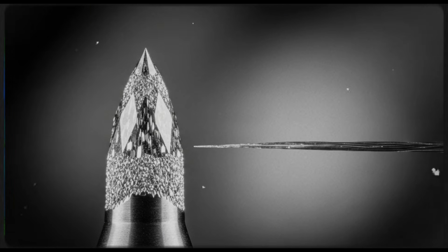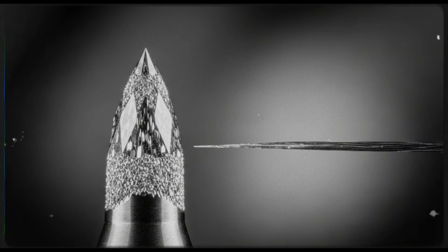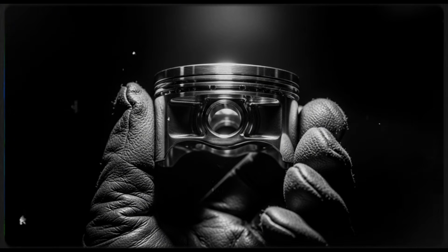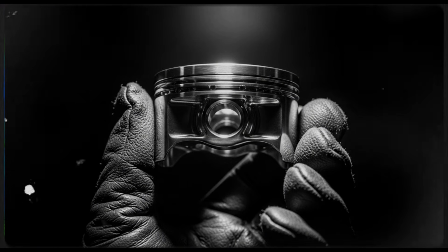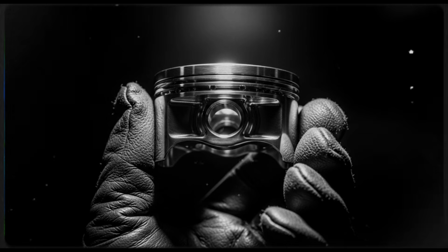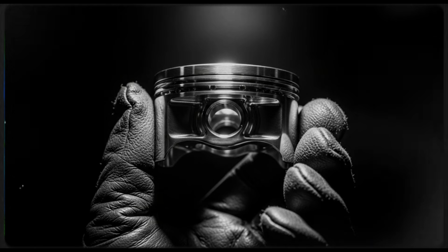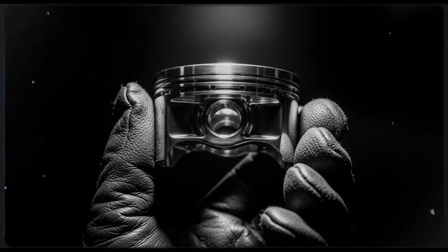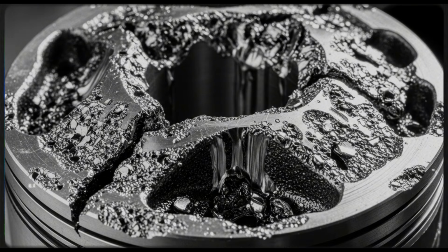There was one major obstacle. No one had ever managed to reliably apply a chrome plate to a piston ring. The electroplating process involved immersing the component in a chemical bath and running a powerful electric current through it. Chrome ions would then meticulously bond to the metal surface. The resulting layer was only 5/10,000ths of an inch thick, slimmer than a human hair, but its hardness was off the charts, measuring 70 on the Rockwell C scale.